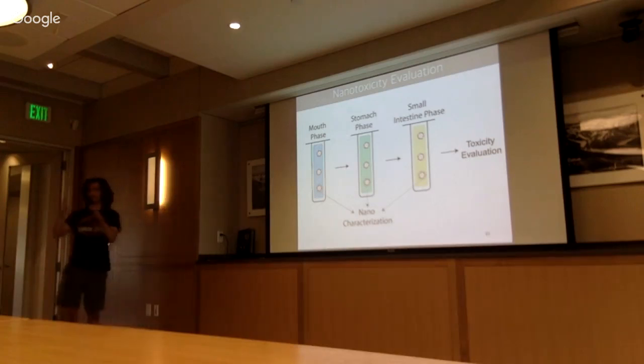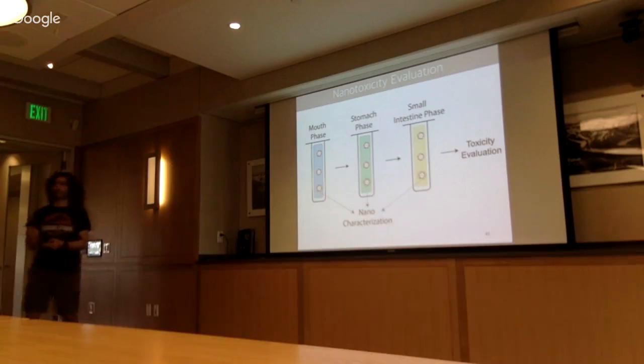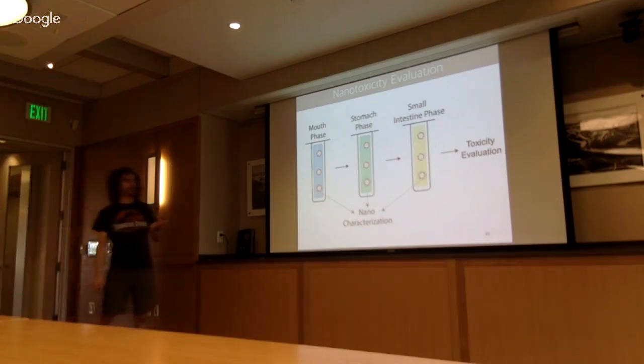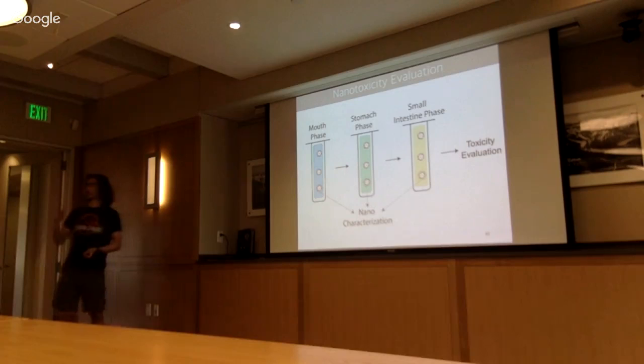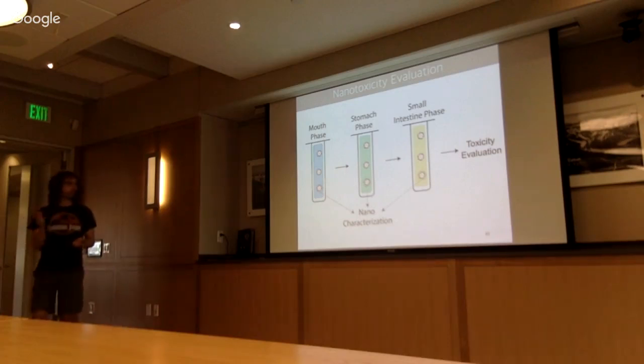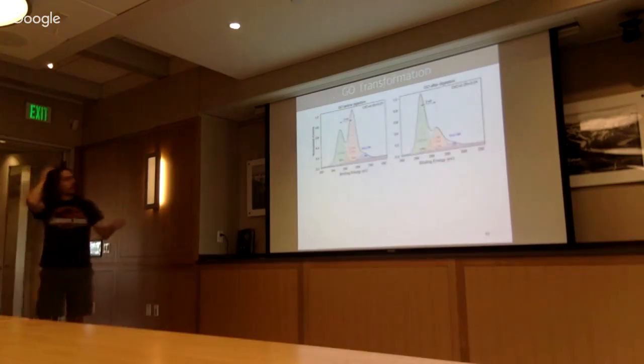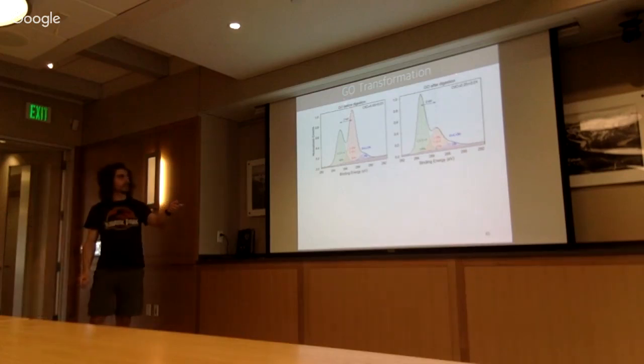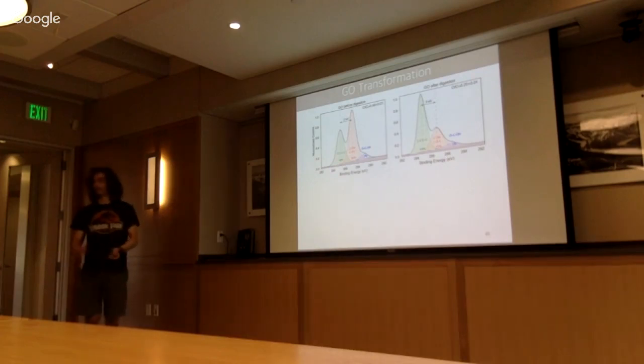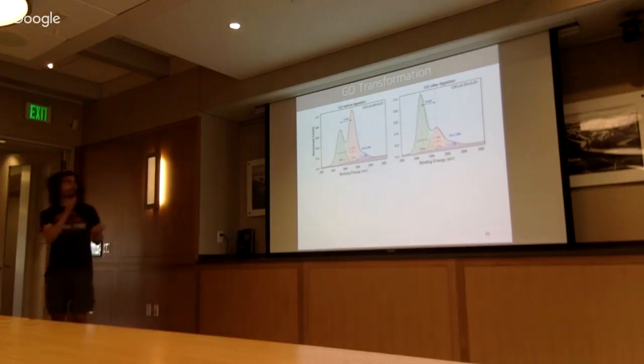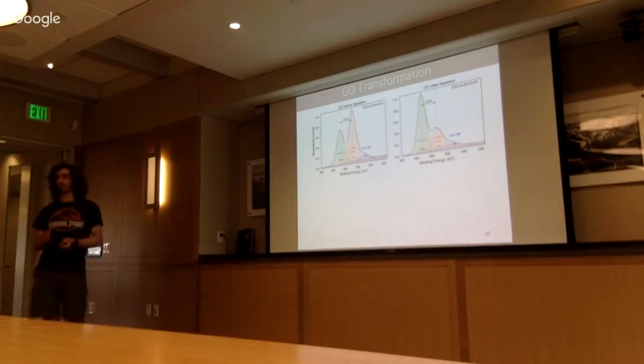It's nothing too fancy, it's basically just a beaker that resembles these three environments. And after that, we are checking the toxicity of this graphene oxide. In the meantime, we're also checking how the material modifies in this environment. So let's see what happens. On the left, you see graphene oxide before digestion, and on the right, after digestion. And we can see that the chemistry is really changing. It goes from an oxygen to carbon ratio of 0.5 to 0.25.